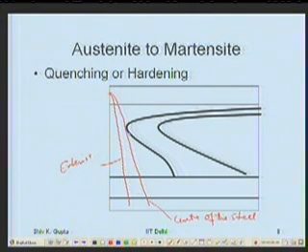Even then, plates cannot fill the whole volume, so there is retained austenite. Plate is a lenticular shape, it cannot fill the space. Laths, which are the shape of a ruler, can fill the whole space. So if we get about 100% or 99% martensite, it is when it is in the lath shape. When it's a plate shape, we don't get that much martensite.